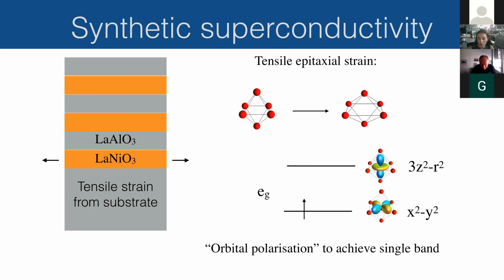So you would expect the in plane orbitals to now be at lower energy because they have more space between them and the oxygens. And similarly, the out of plane orbitals should go to higher energy. If you split this enough, then hopefully what you would have is that your 1 EG electron should just stay in one band. You will have then one band at the Fermi level. And this looks a lot like cuprates.